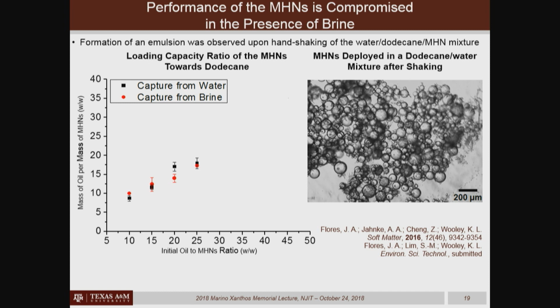And so what she did was she backed off from studies on crude oil, instead working with dodecane as a model hydrocarbon material. And what she found was that she was shaking the samples and even vortexing them to try to get more dodecane to be captured by these materials. And ultimately, she started seeing these emulsions forming. And the emulsions could form in water, but as you know, when you're in the laboratory and you have an emulsion, you add brine to salt things out, right, and to break up the emulsion.